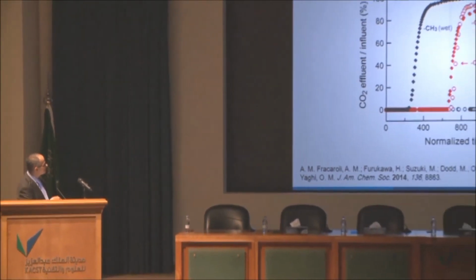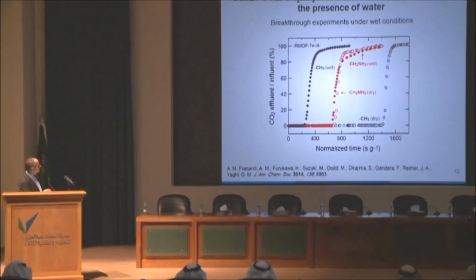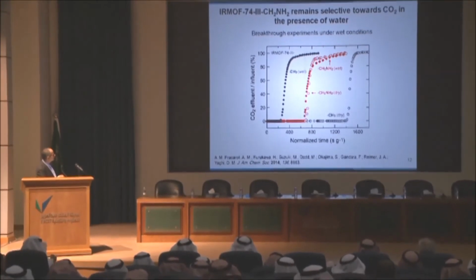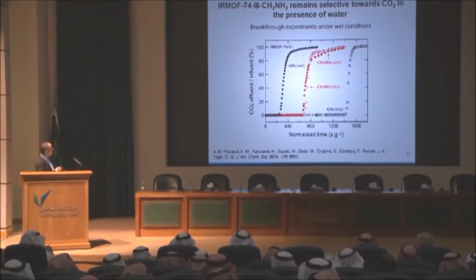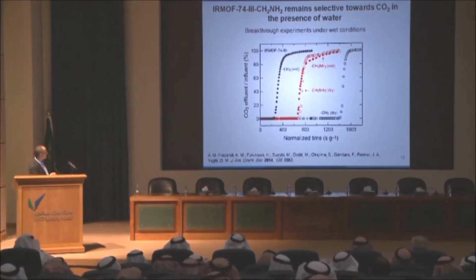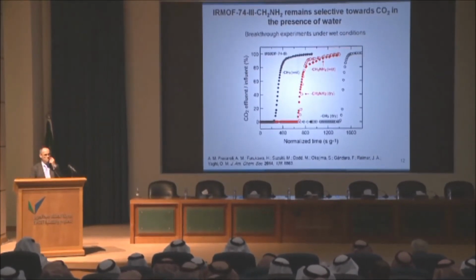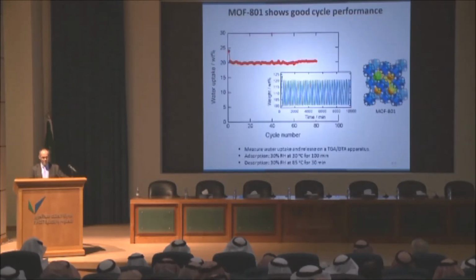The efficiency of the material is not altered. While a material that's not functionalized, like methyl material, you can see that the efficiency drops as you introduce water. The breakthrough time drops significantly, almost to 0. So this is the kind of precision that I'm talking about, fashioning the interior of the MOF to overcome tremendous challenges.